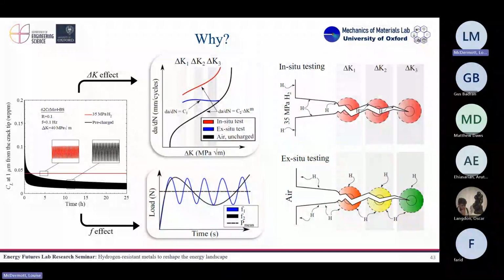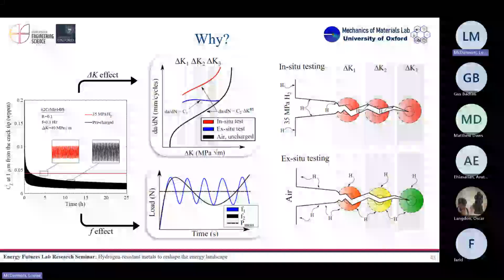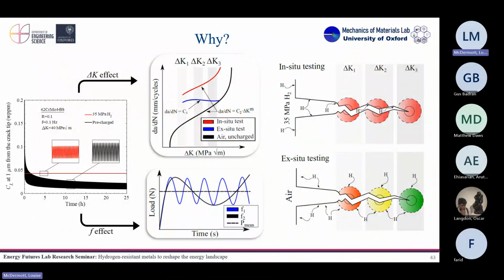And that can also explain the frequency behavior. It's very easy, it's actually the same explanation. When you have hydrogen outside that you can feed infinitely to your crack front, it doesn't matter how fast you load and unload the sample, okay? Because hydrogen doesn't need to flow slowly to your crack tip, like happens here, okay? If you don't give the hydrogen in the surroundings of your crack enough time to diffuse to your crack, and your crack is growing so fast that hydrogen cannot catch up, then you don't have embrittlement.